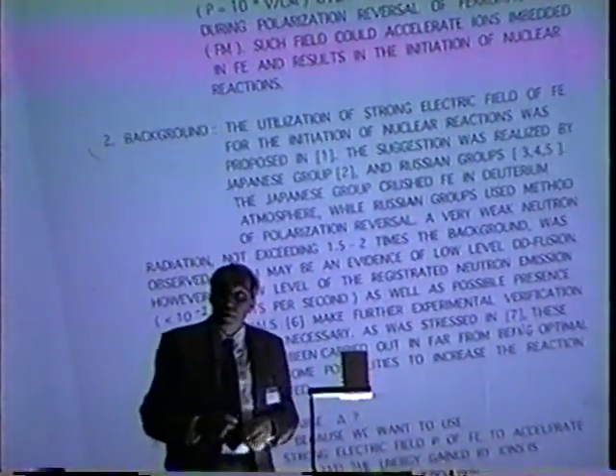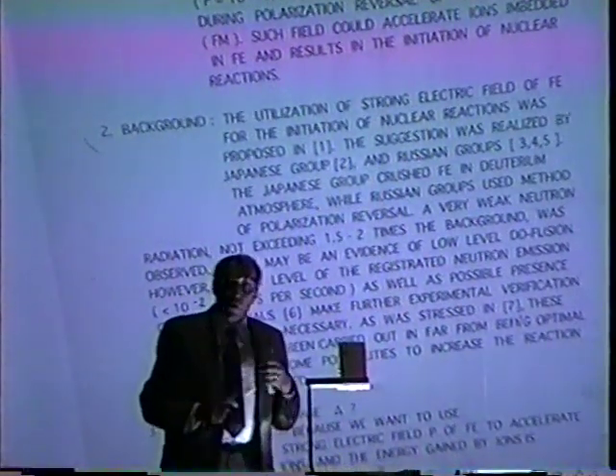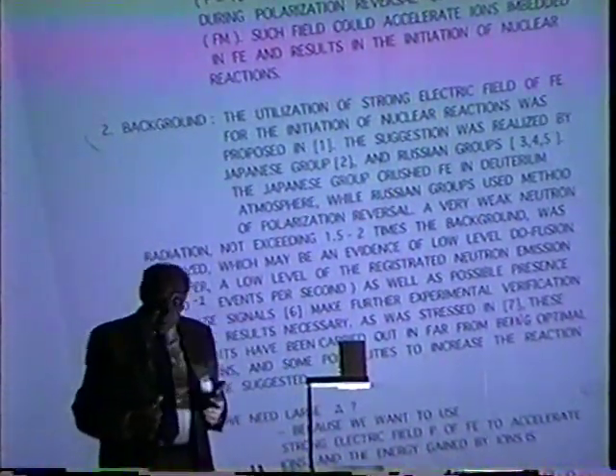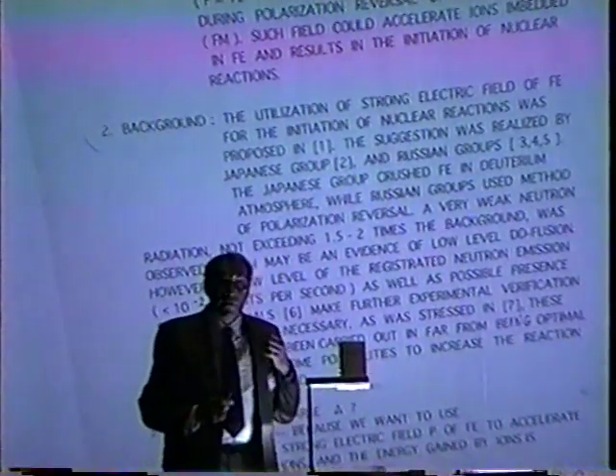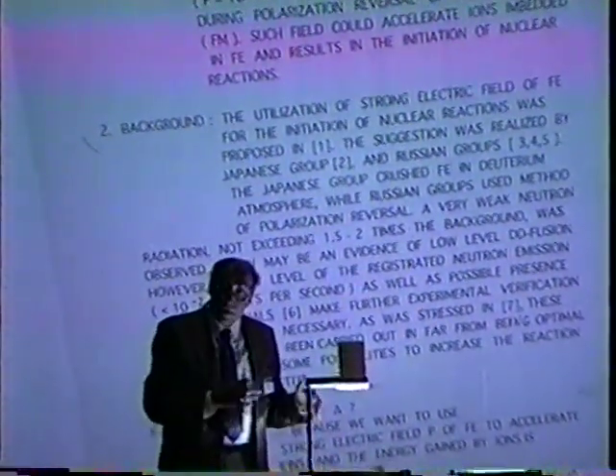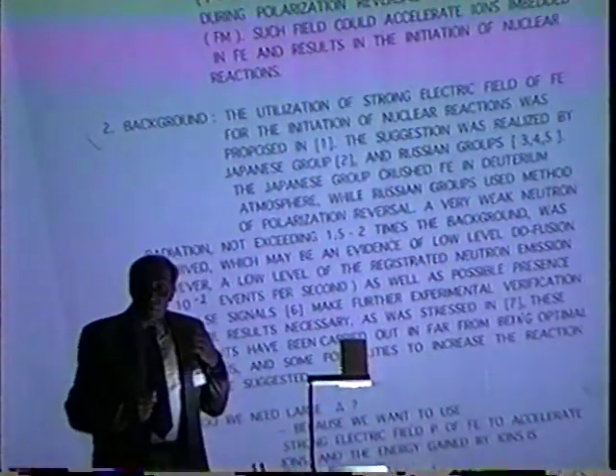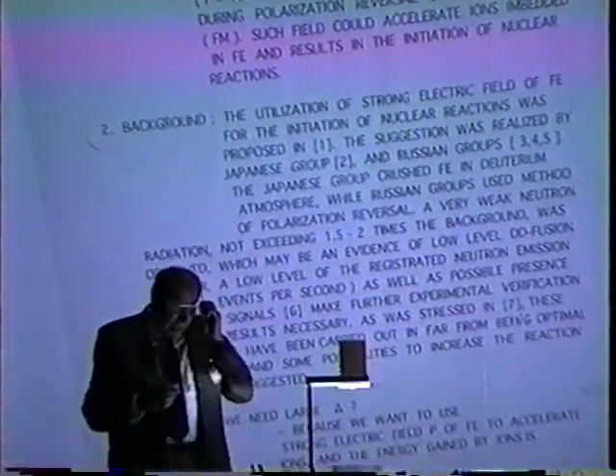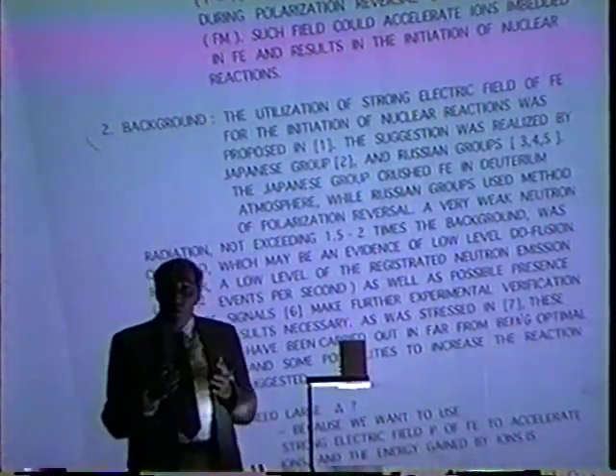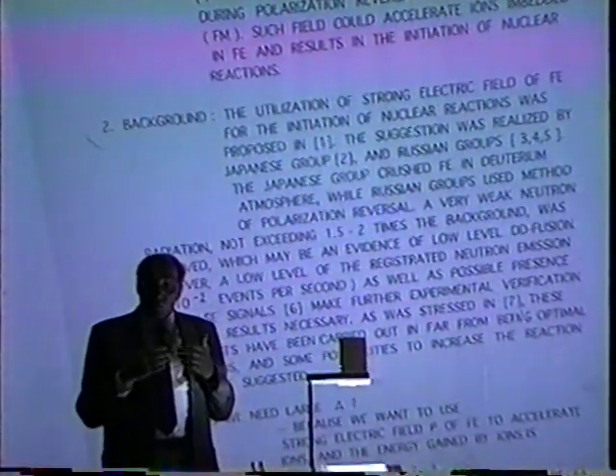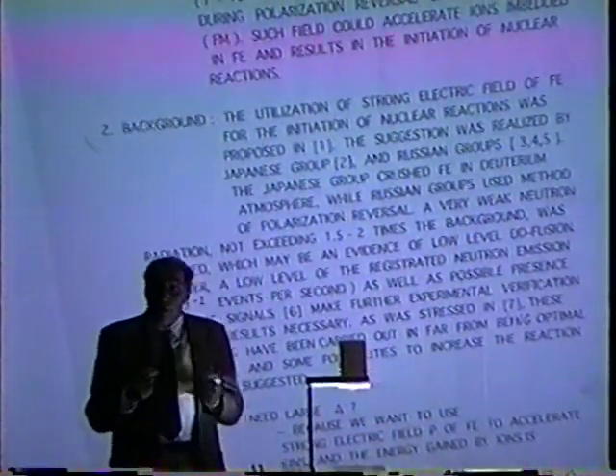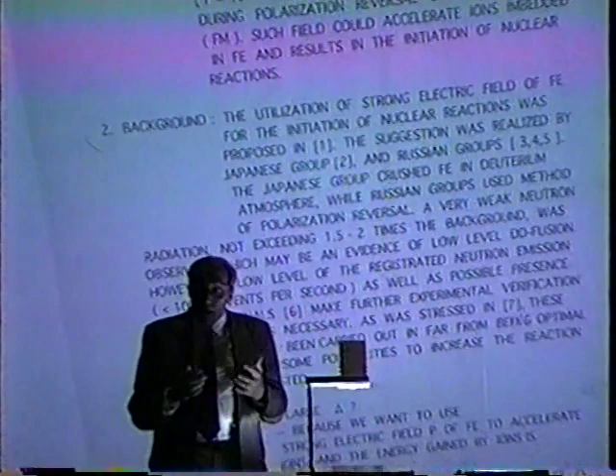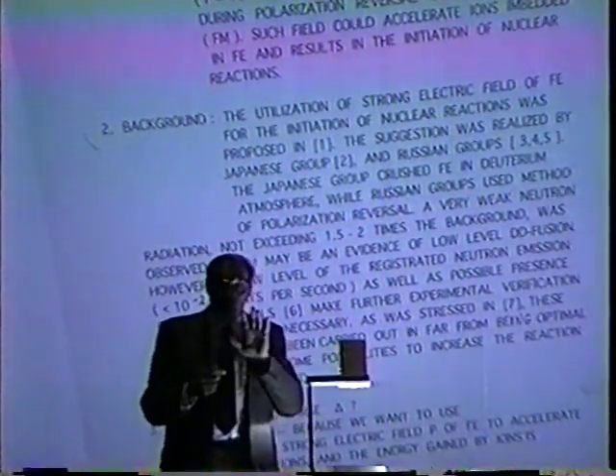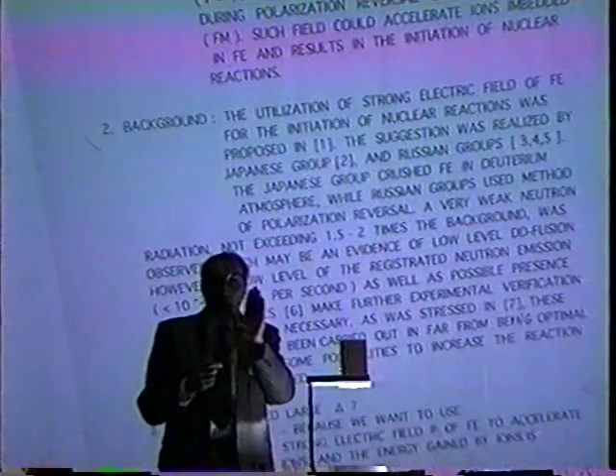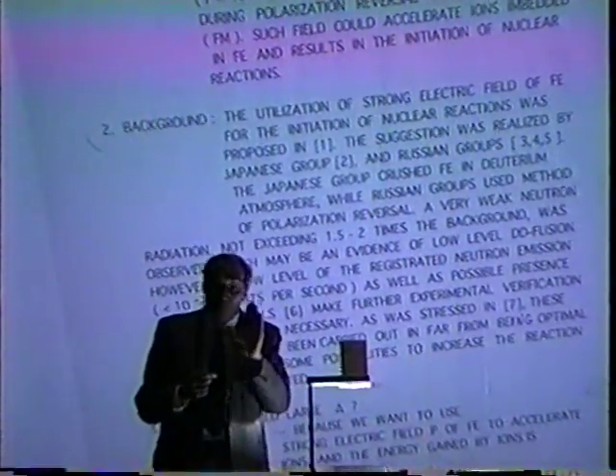In fact, some years ago we initiated this activity. However, all experiments which have been done after that were done with far from optimal conditions. So we are discussing how to make these conditions more favorable. And the main idea is that the main problem is tunnel breakdown. How to avoid this effect? It is possible if you create some instability. And for that, you need a special shape of pulse, with a very large, very steep front.